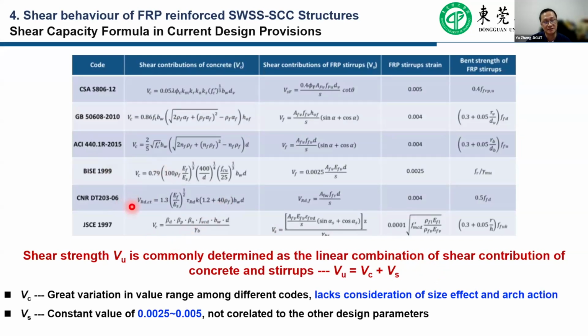But in our current design method, we can find that the total shear capacity for the FRP reinforced concrete is commonly determined by the combination of the shear contribution from the concrete and from the steel stirrups. However, we can find that the current design standards for shear capacity prediction show great variation across a wide range among the different models, and lack consideration of the size effect and the arch effect. And a constant value for the effective strength is used to predict the contribution of the FRP stirrups.